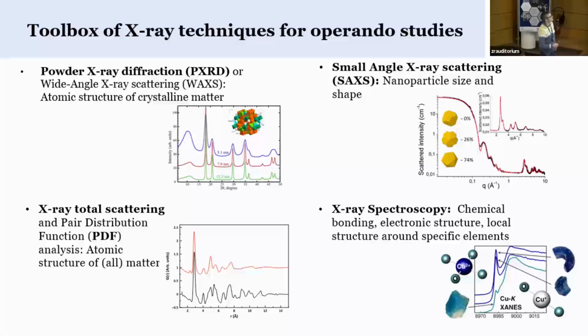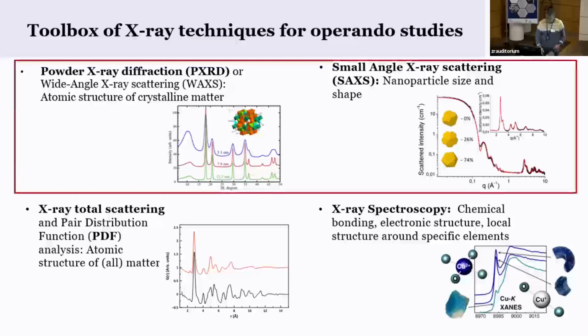And so there are different X-ray tools available. You have the powder XRD, the small angle X-ray scattering. We also, in collaboration, look at total scattering and X-ray absorption spectroscopy. Today, I focus on the two, powder XRD and small angle X-ray scattering, but we also, for example, on the Swiss-Norwegian beamline, combine these two. And it's really the combination of different methods that is very powerful. So that's really a specialty here at the ESRF, where you can get much more information if you are able to combine two methods in the same measurement.